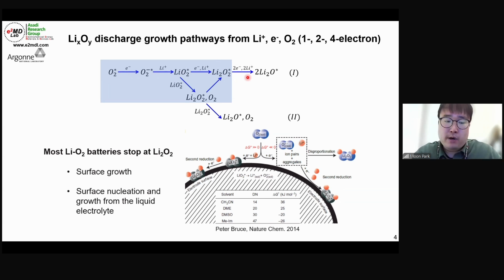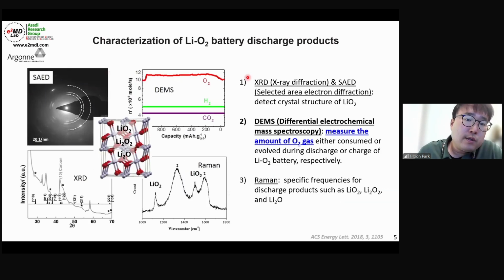However, in this paper, we found that it could be done at room temperature. In 2018, Linda Nazar's group published a Science paper showing the reversible 4-electron reaction at high temperature, such as 150 Celsius. But this paper shows the 4-electron reaction is possible at room temperature, and I will show the detailed results in later slides.